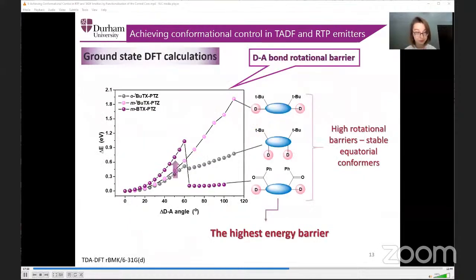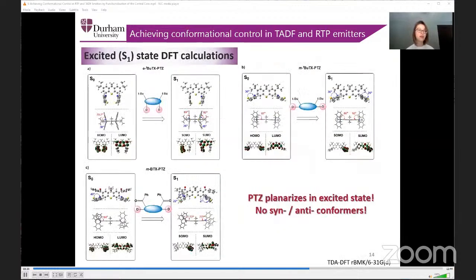Additionally, by swapping the tert-butyl for the bulkier, electron-accepting benzoyl group, we were able to enable TADF in this molecule. To check whether we are ending up with stable equatorial conformations as we wanted, we ran ground state DFT calculations, and here you can see the energy scans proving the stability of the equatorial conformer. Thus, we can see that the barrier needed to twist the molecule by a certain angle, for example 20, 40, 60 degrees, is quite high. This is direct proof of the stability of the equatorial conformation, which is the highest in the benzoyl-substituted compound. Further on, we proceeded with computing the first singlet state properties.